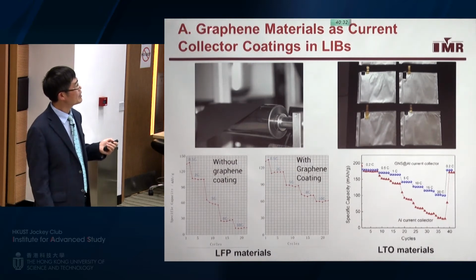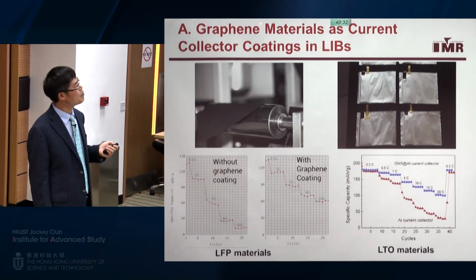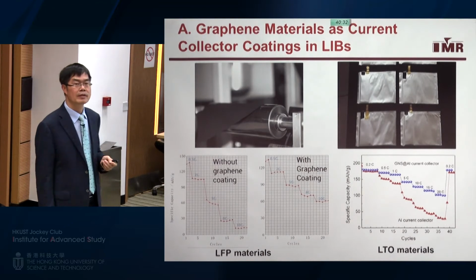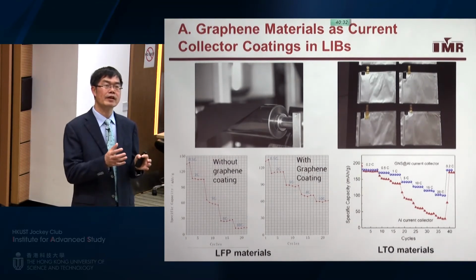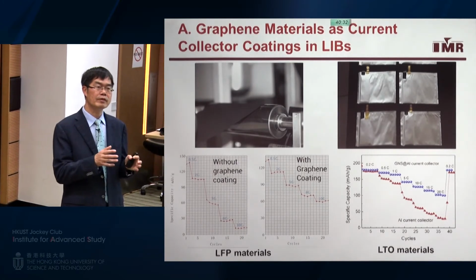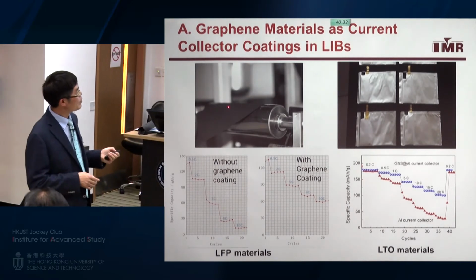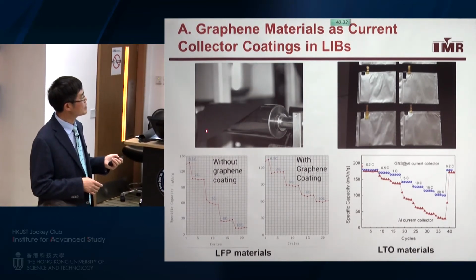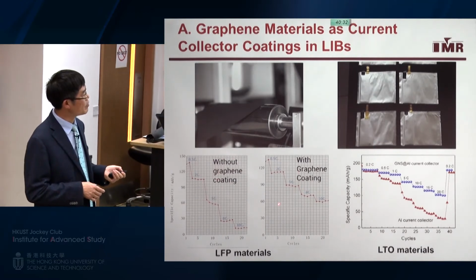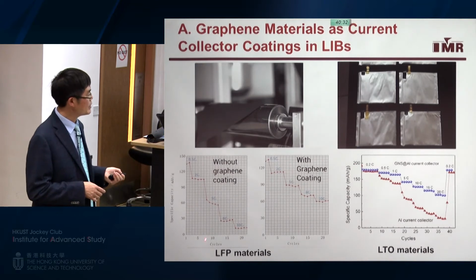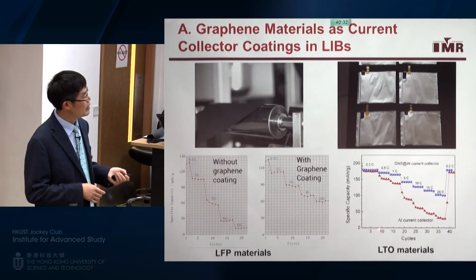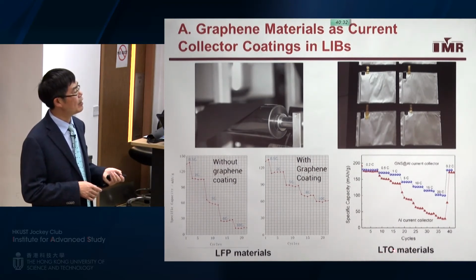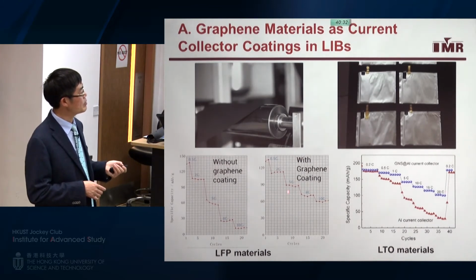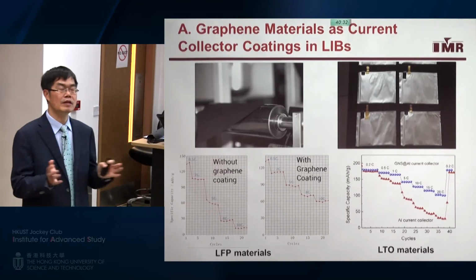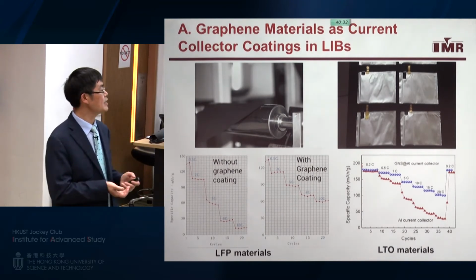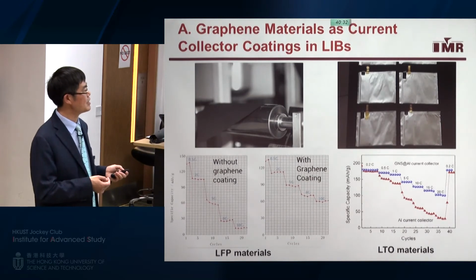The first example is a practical application. We can simply use graphene as a current collector coating. As I just mentioned, in a battery we have to use a current collector, normally copper foil or aluminum foil. If we coat a very thin layer on the current collector, you can see without graphene coating and with graphene coating, the performance has been greatly improved. This is lithium iron phosphate, a very popular cathode material, and this is lithium titanium oxide, an anode material. You can see for both materials, the performance has been improved. This is a very simple one, so we don't publish any papers. We have a patent, and one company is trying to use it in industry.